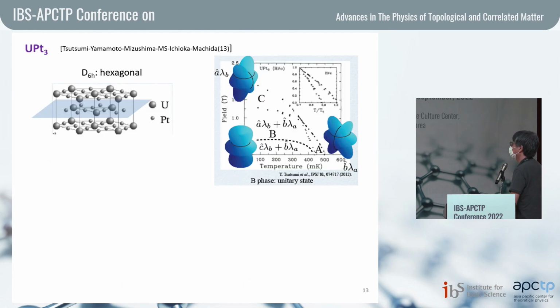For example, let's consider UPt3. As I mentioned before, UPt3 has a mirror reflection symmetry with respect to the z direction. Here I show the theoretically proposed phase diagram for UPt3. This is the temperature, and this is the magnetic field in the z direction. Here we should note that the magnetic field in the z direction does not break the mirror symmetries. So we can apply the argument in the previous slide to this phase diagram.